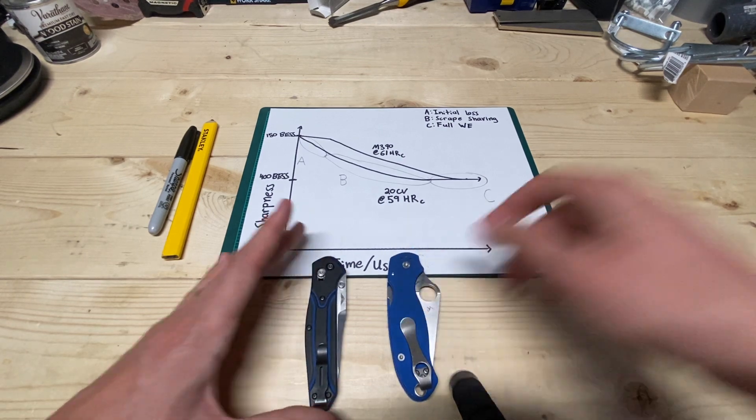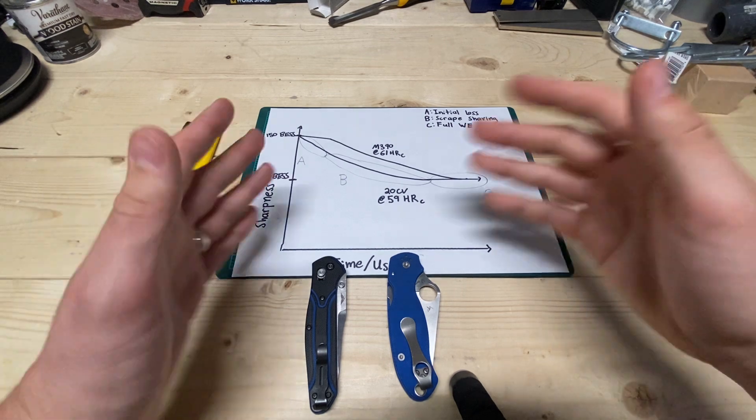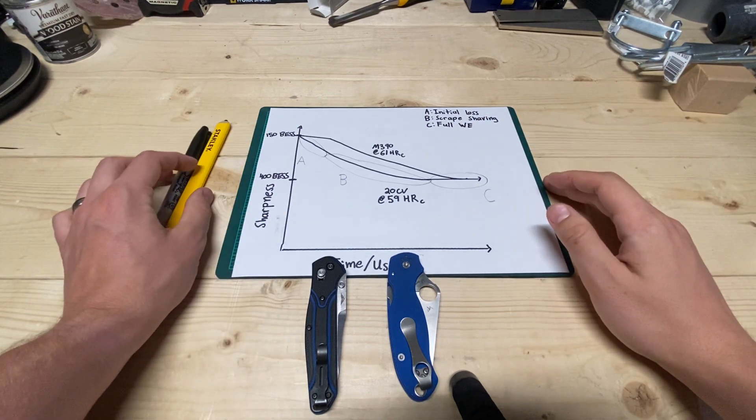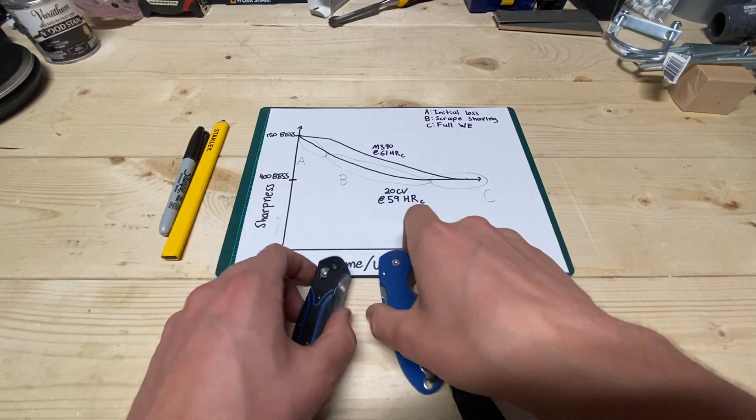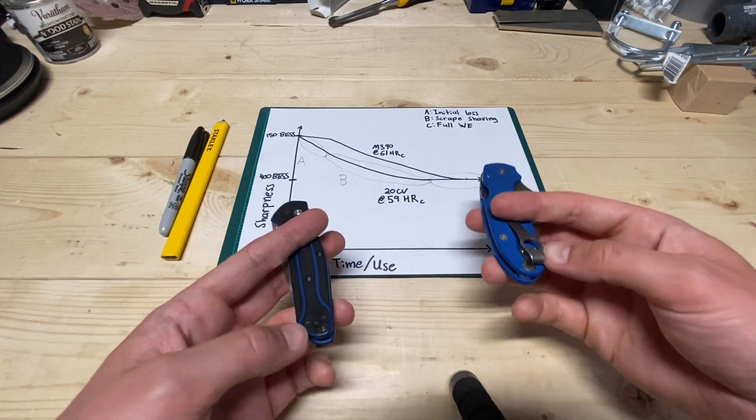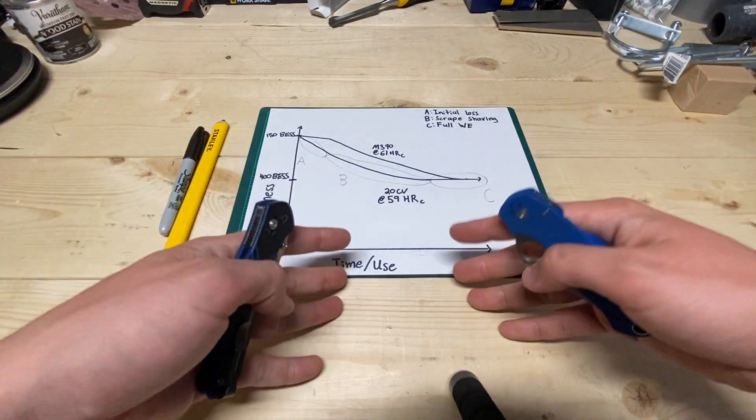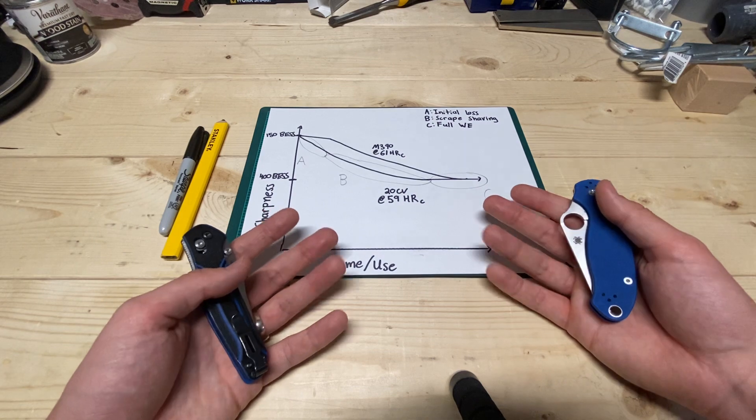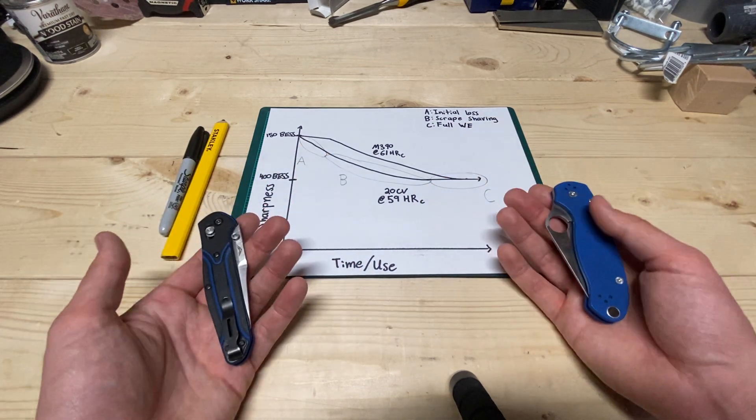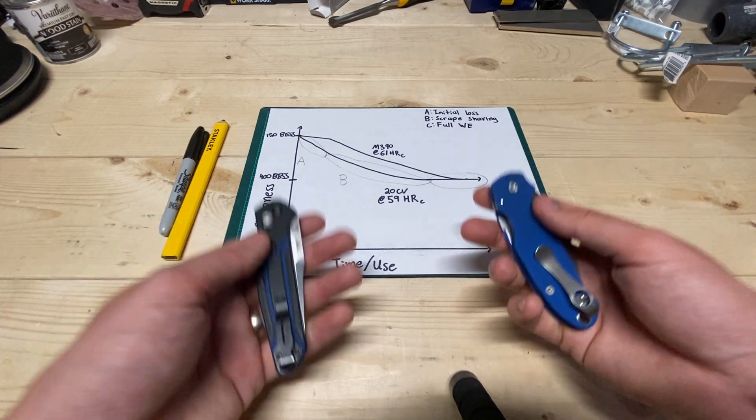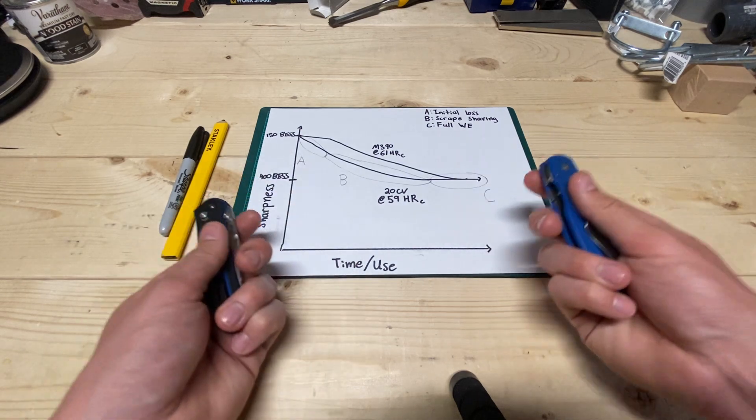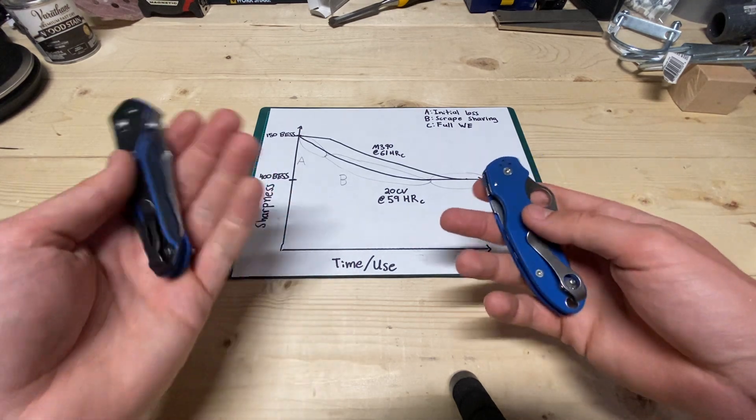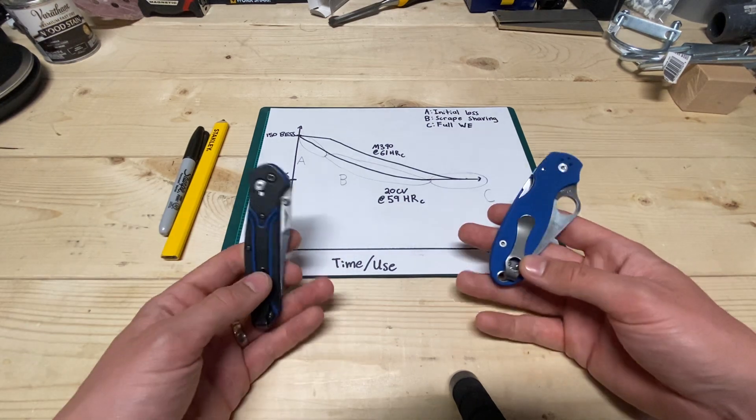The point is I put out a video about the breakdown of PM steels, particle metallurgy steels. The specifics on the particle metallurgy is that with steels, there comes a point when you're putting so much alloying elements into the steel that you basically have to do particle metallurgy, otherwise it's just too fragile using traditional methods. So PM steels generally will have higher carbide contents, just because if you don't have that much alloy in it, you don't need to PM it.